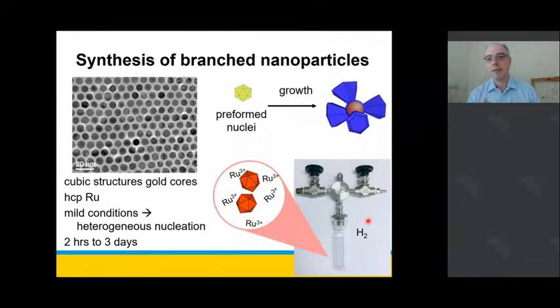So the hydrogen gas is a very, very mild reducing agent. And it's the hydrogen gas that will reduce your metal ions down, say, from ruthenium-3 to ruthenium-0. But it is a very mild reducing agent. And this is the key or the trick to give us this very slow trickle of our ruthenium metal atoms. And then they'll nucleate and grow onto our gold seeds that we put into our solution. So as I said, we tend to be quite relaxed about how we're doing our chemistry over here in Sydney.